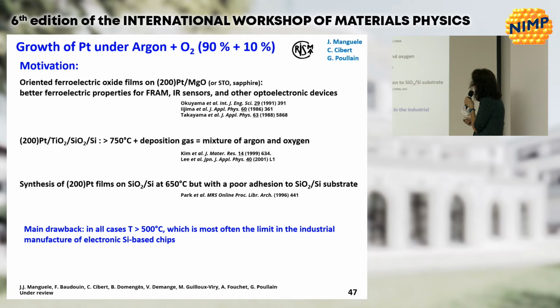And the second part of the study was to look at the platinum under argon plus oxygen. And the motivation is the following. It was shown some years ago that if you have the 200 orientation for the platinum, you have better ferroelectric properties for a number of devices. But the problem is that to obtain this 200 orientation, we need to work at very high temperature, and also we need to work with a mixture of argon and oxygen.